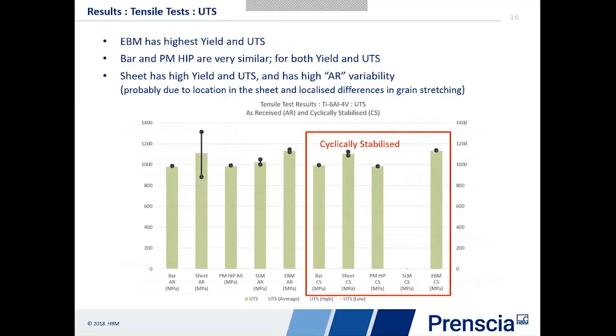The first thing that you notice is that we have quite a bit of scatter on the sheet in the monotonic test. And that's really the reason why we do cyclically stabilized tests in this case. The sheet and the rolling process can induce residual stresses, and that can give us scatter. By doing that cyclically stabilized test, it reduces that amount of scatter somewhat. So the interesting thing here is that when we look at those tensile properties in UTS, there's no real difference between the powder metal and the additive manufactured from the wrought materials.